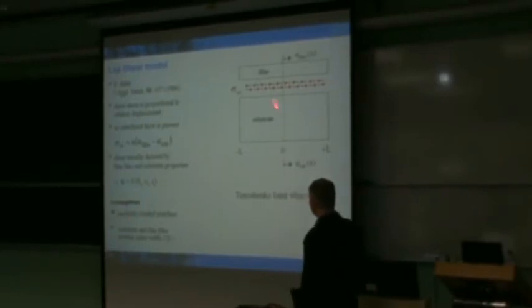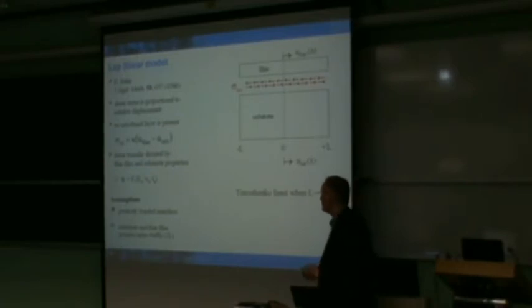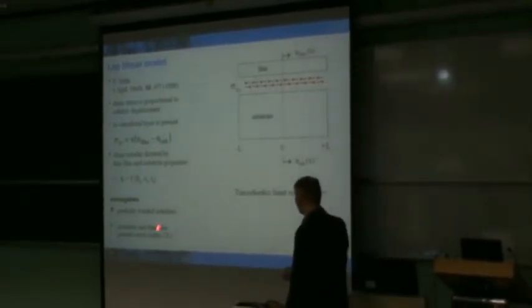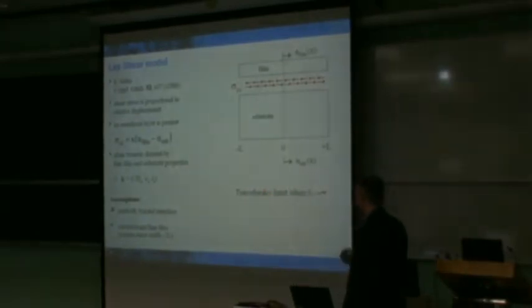But if you assume that there's perfect bonding between the film and the substrate, you basically create a contradiction. There's no way that you can really get slip in these systems and therefore generate a finite shear stress and still have a perfectly bonded interface. Nevertheless, this model still persists in the analysis of these structures. There are still a couple of other limits that go with the behavior, but what we'll show later is that this proves to be unsatisfactory, let's say, in describing the mechanics.